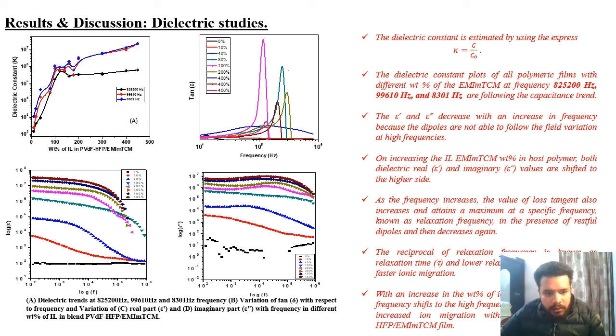And in the lower two graphs, you can see the real and imaginary parts of the dielectric versus frequency, where you can see that in both cases the real and imaginary parts are increasing with increasing weight percent, and when we increase the frequency they start to go downward, because the dipoles are not able to follow the field variation at high frequencies.